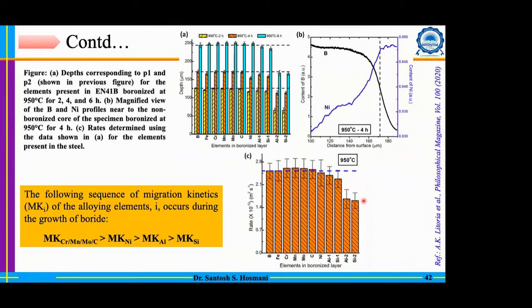And in the case of aluminum and silicon, you have two types of migration. One migration is in front of the sawtooth boride, and one is between the borides, that means in the matrix. The migration in front of the boride is still less severe, and it is able to migrate at a fast rate. However, the elements accumulated between the boride columns are unable to migrate at a faster rate, and that is restricting the lateral growth of this boride layer.